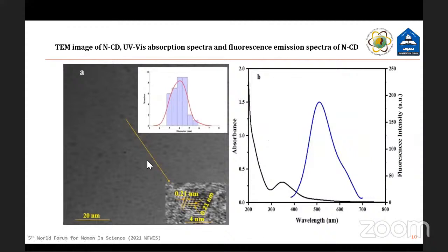TEM image of nitrogen-doped carbon dot, and UV visible absorption spectra and fluorescence emission spectra. Here we mentioned, as we can see, 4 nanometer, and the distance between the lattice planes is near 0.21 nanometer. And here is the size distribution of our nanoparticle, which shows that most of the nanoparticles that we get have 4 nanometer in size.